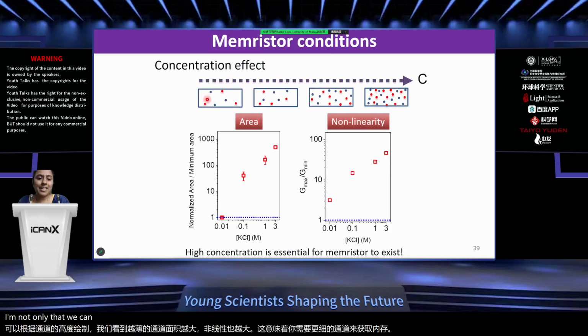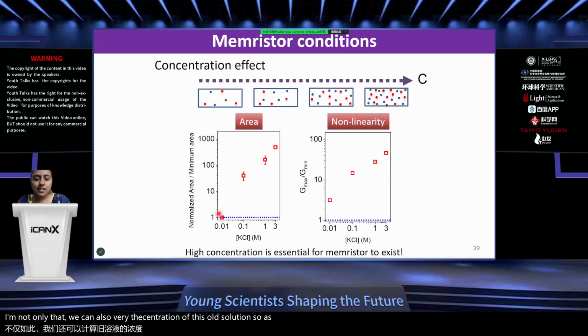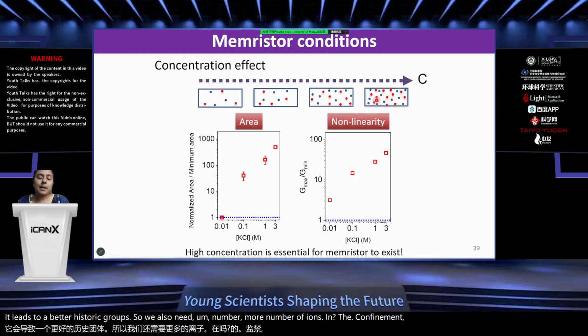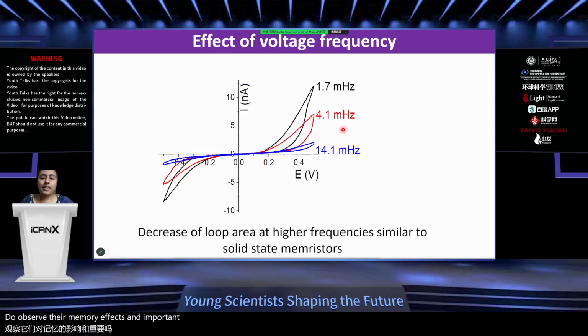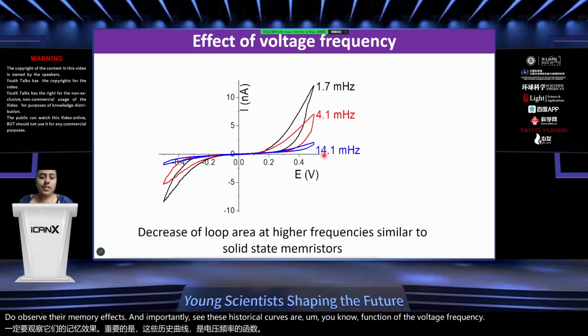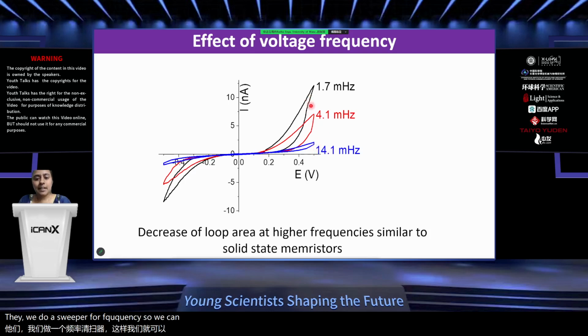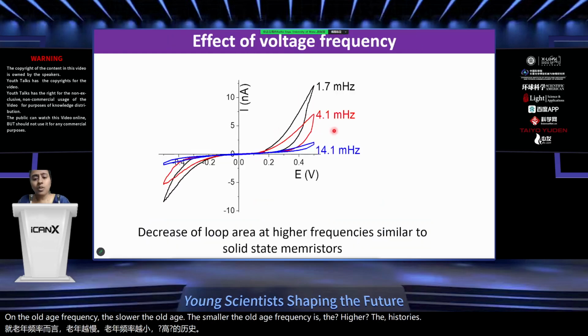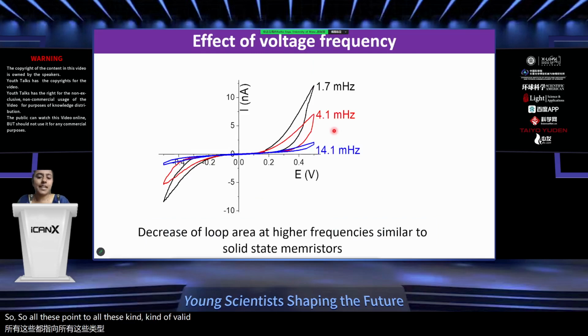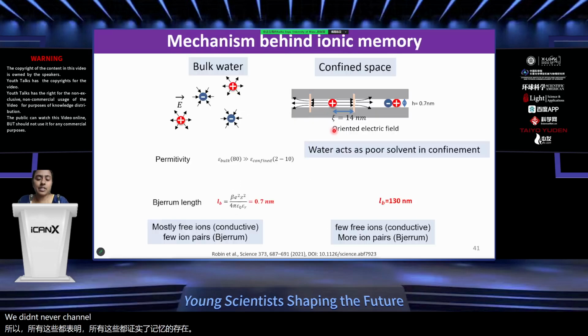And not only that, we can also vary the concentration of the salt solution. As the salt solution concentration increases, it leads to better hysteretic loops. So we also need more number of ions in the confinement to observe the memory effects. And importantly, these hysteretic curves are a function of the voltage frequency. If we do a sweep of voltage frequency, we can see that there is a dependence on the voltage frequency. The slower the voltage, the smaller the voltage frequency is, the higher the hysteresis. So all these validate that there is a memory within our channels. And why does this happen?